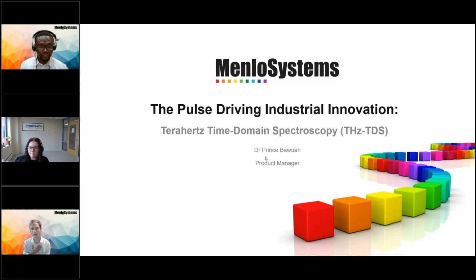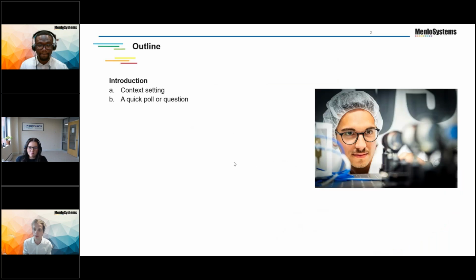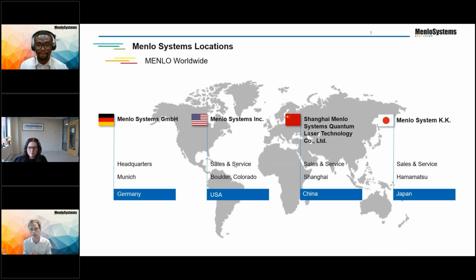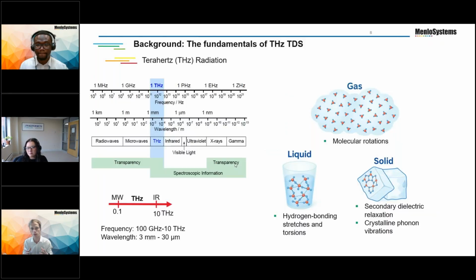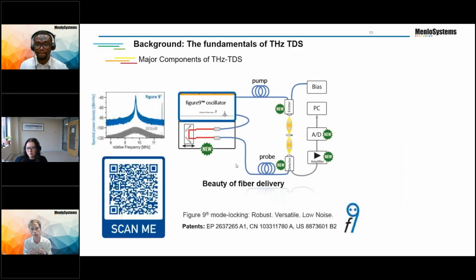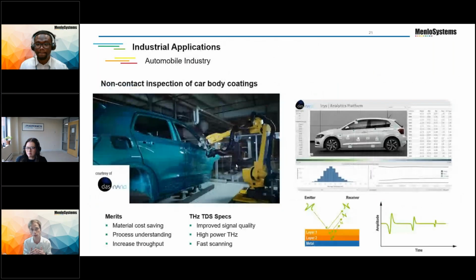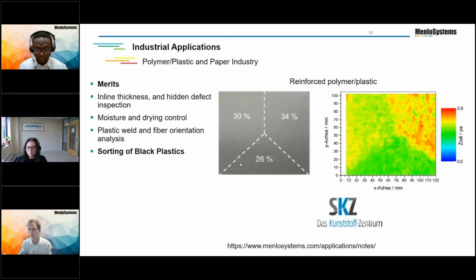I have to confess I am not an expert in those materials, so I'm not 100% sure. From what I do know of glass fabric reinforced thermoplastics, my understanding is it's a polymer material where fibers are used inside of it in order to strengthen that polymer. In terms of looking for defects in that, it would really depend on the defect size you'd be looking at. Typically when looking for defects or imperfections in a material, you're usually limited by the spot size of your terahertz beam at focus. Typically this is around 250 microns or so.